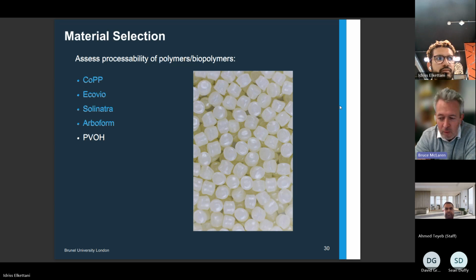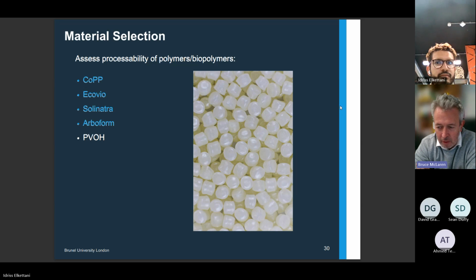Arboform is basically wood in a very, very simple term, and PVOH. We did trials with both cold water and hot water PVOH. Probably one of the most common uses of PVOH is that very, very thin film that goes around your dishwasher tablets and things like that. But it's getting used in more and more applications at the moment. But it is moisture sensitive. And all of them, they're not quite as easy to process as a good old polyprop. But it was very, very interesting.